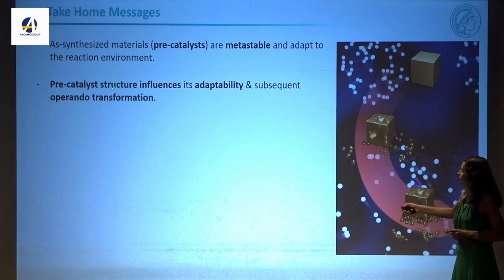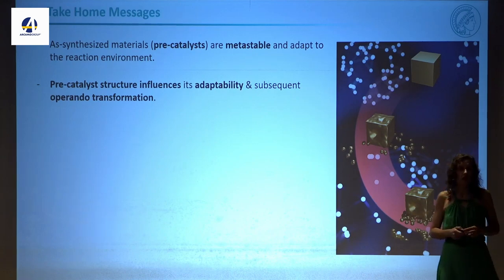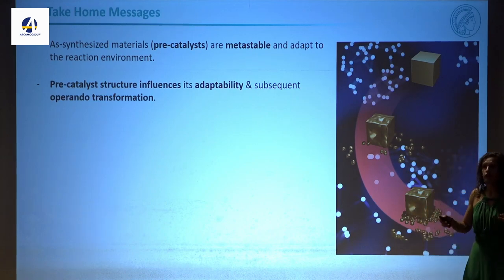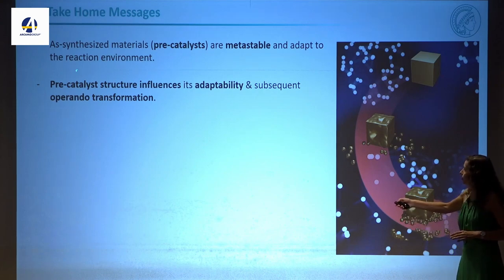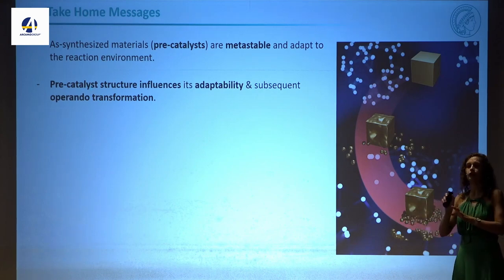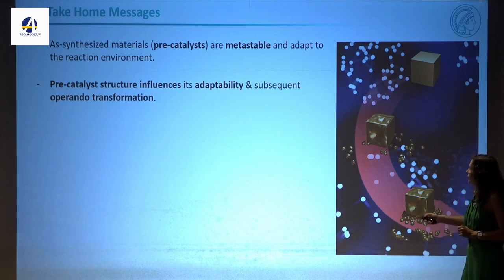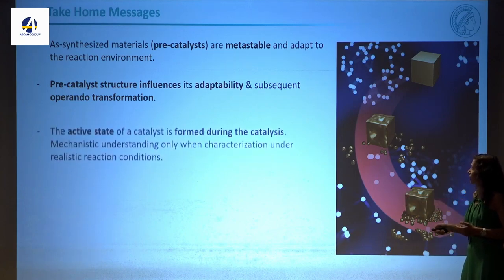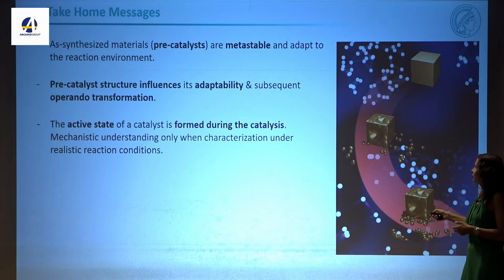The pre-catalyst structure, however, influences the adaptability and the subsequent operando transformation. So if you are a synthetic chemist, not everything is lost. If you are able to tune the pre-catalyst structure, you are going to influence how this performance is going to change. But the reality is that knowing everything about this is not going to tell you what the active phases are. The active state of the catalyst is formed during the catalysis.